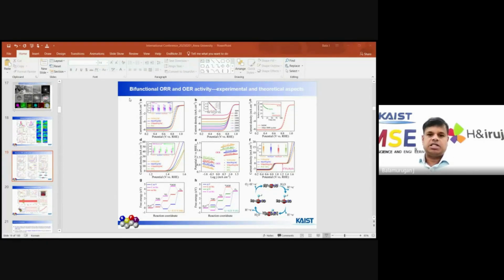We also test the optimal catalyst at different rotation speeds of ORR. When increasing the rotation speed, the current density drastically increases towards more negative current density values. In the durability test, before and after 5,000 cycles, the performance is almost maintained. There is not much loss. And you can see the durability compared to the platinum.